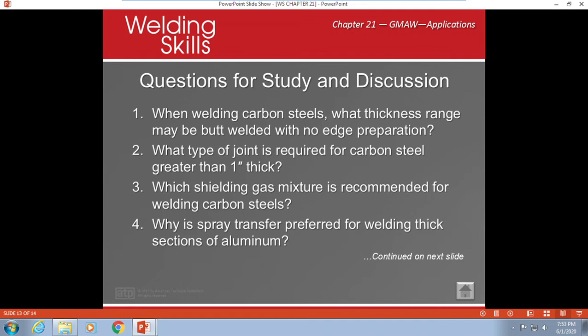Okay, which shielding gas mixture is recommended for welding carbon steel? So, for carbon steel, shielding gases with GMAW are straight CO2 or an argon-CO2 mixture. For short circuit on carbon steels and low alloy steels, a 75-25 mixture is preferred, 75% argon and 25% CO2. Carbon steel welding with spray transfer can be used at 95 to 98% argon and a 2 to 5% oxygen mixture. Straight CO2 may be used for high-speed production welding, and pulsed spray transfer can be performed with 90% argon and 10% CO2.